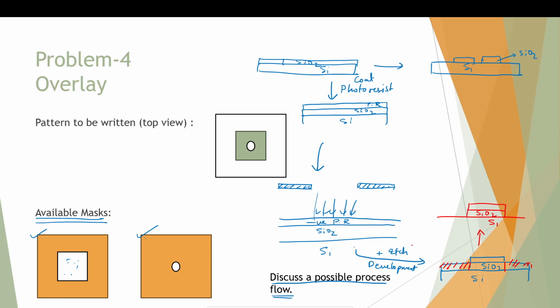So how do we etch it? We can use some dry etch technique. Silicon dioxide we can mostly etch with a dry etch, fluorine chemistry, reactive ion etching. So we can use something like that, RIE. We will learn about the etching techniques in the next classes, but for now just know that we can etch away SiO2 while protecting the part that we require with a photoresist. Okay, so now I need to remove the PR.